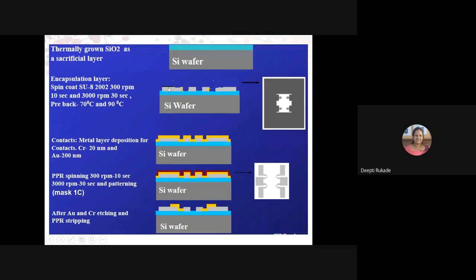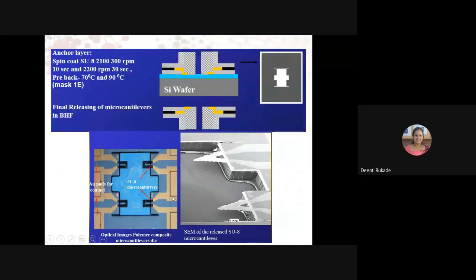Then after that, once you pattern this SU8 resist, you need contacts. For contacts, we normally use chromium gold. So here we have 20 nanometers chromium and gold. And then you go for a second level litho, which gives you this red pattern that you can see, this structure. After gold and chrome etching, you'll get something like this.